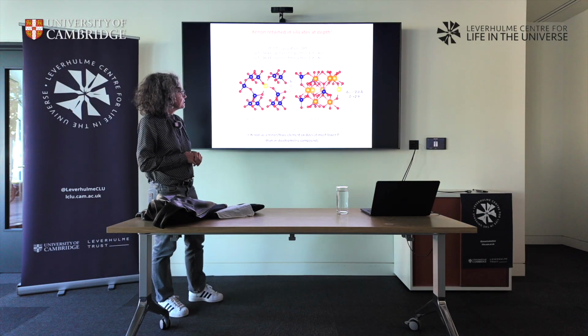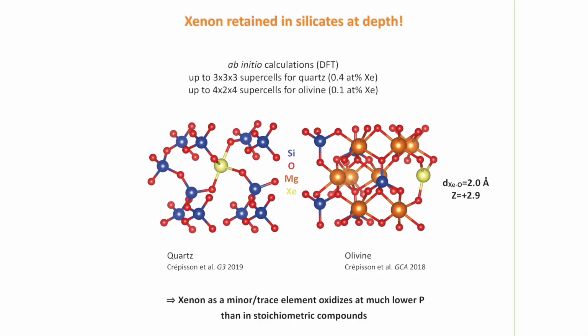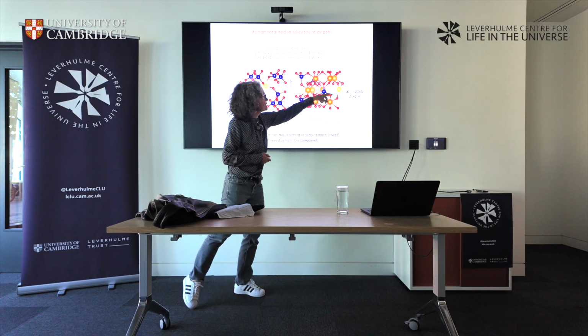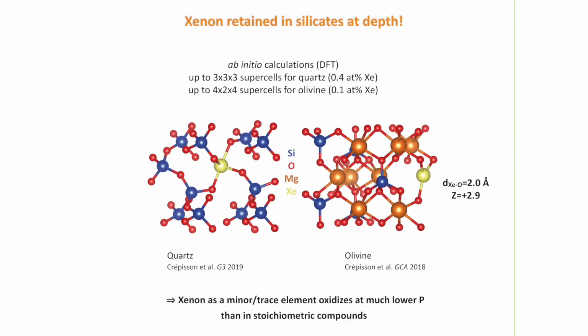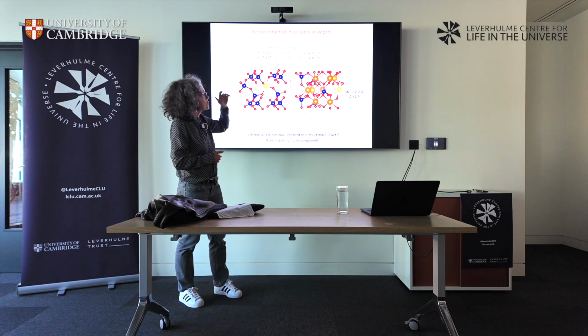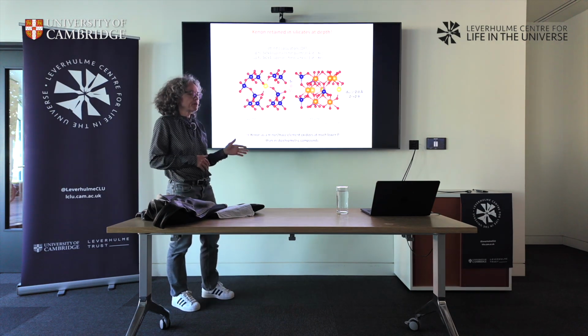Very early we suspected there was some silicon release, but the final answer came when we did ab initio calculations with Céline Crépisson. She was a PhD student at the time. So this is the quartz structure, this is the olivine structure. In both cases, the xenon atom is in yellow, and in both cases it bonds to oxygen atoms, not exactly in the same local configuration, but the bond length is about the same, 2 angstrom, and there is a charge, in this case of almost +3. And this occurs at very low pressures, 1 GPa is enough to induce that.